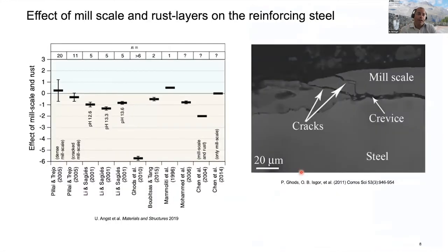So when it comes to the effect of mill scale and rust layers, in that RILEM committee, we looked at different literature studies that reported data on the effect of mill scale and rust layers, and we summarized that in the plot here on the left-hand side. So this plot basically is a normalized version of the different data reported in the different studies. We had to normalize these different data in order to allow for comparison between them.